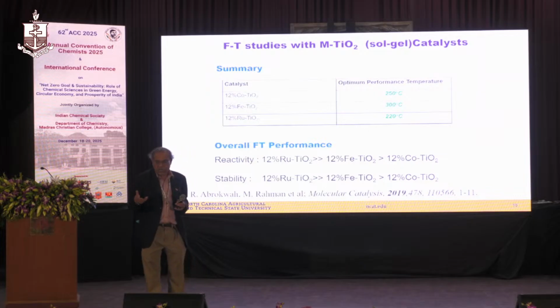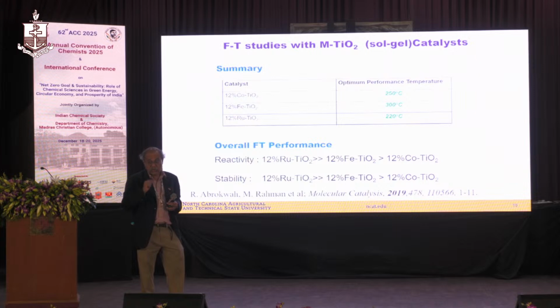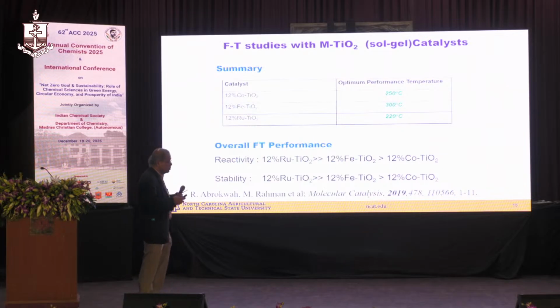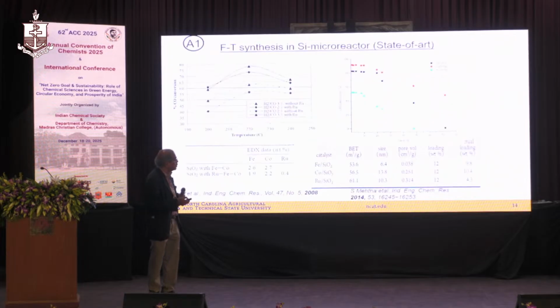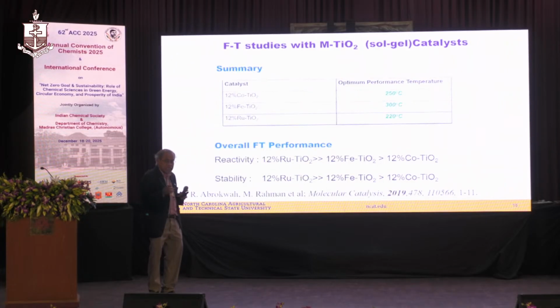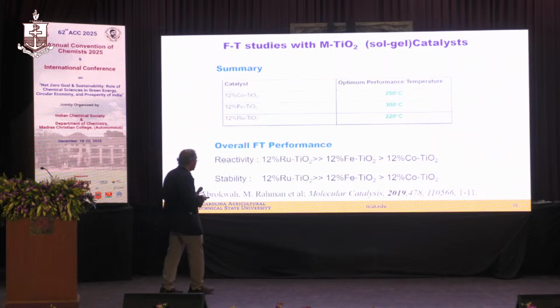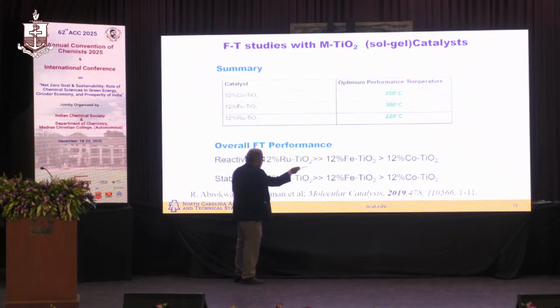When we started this NSF project, one of my students, a chemical engineering student, Mahabub, was telling me, Professor Kuila, have you looked at the effect of all these supports on individual metals, especially in a microchannel microreactor? I said, no, you can do your thesis that way, and I'm going to make the story very short. So he went to the titania sol gel, and what he found is exactly opposite of what I just showed you. I showed you that in the silica sol gel, ruthenium deactivates very fast. But now, if you put titanium, everything is opposite. Ruthenium is more stable than the iron or the cobalt.